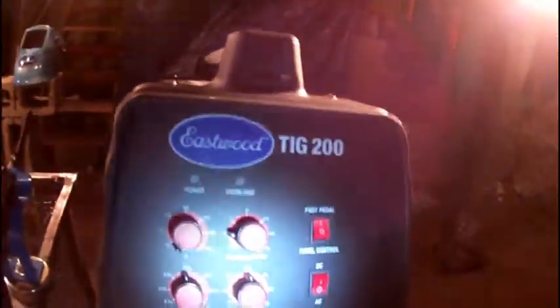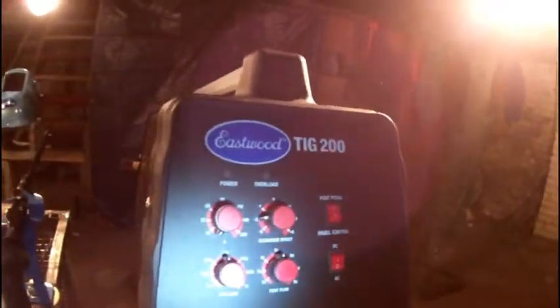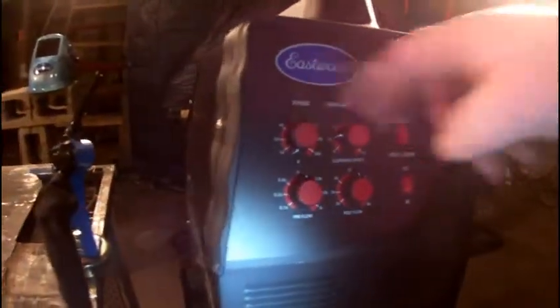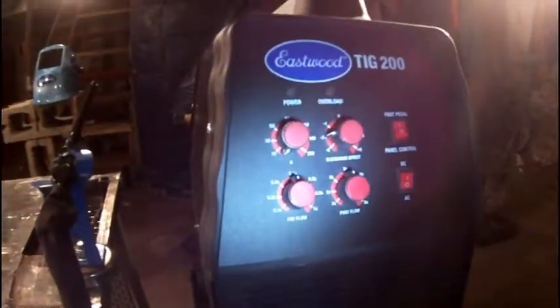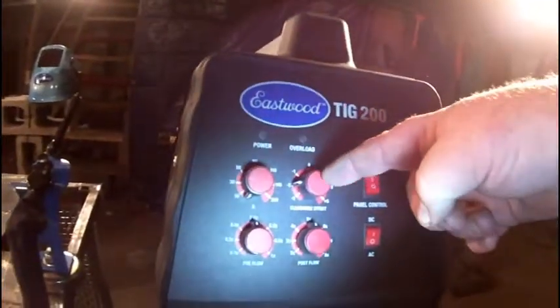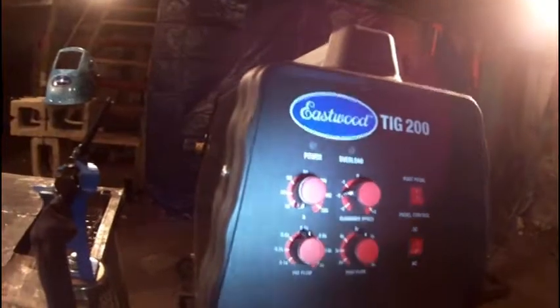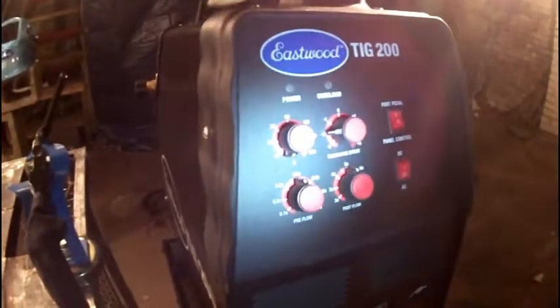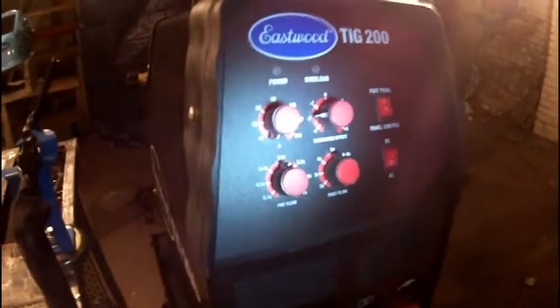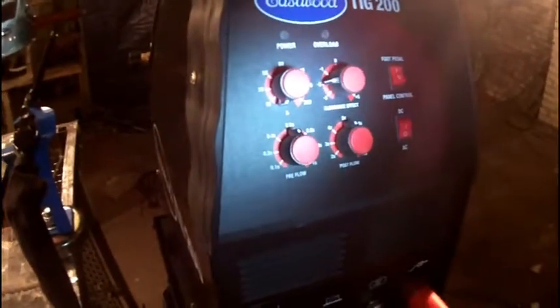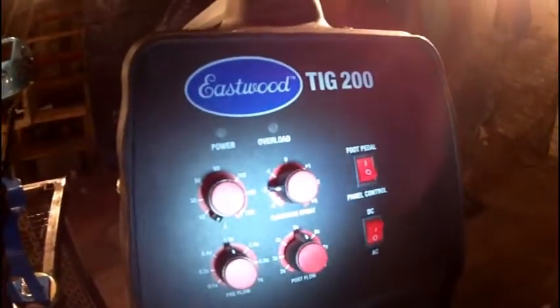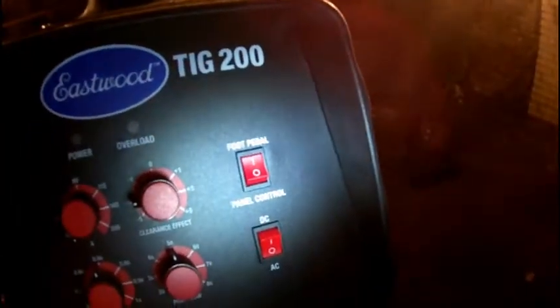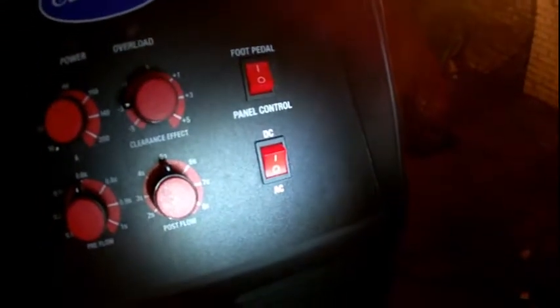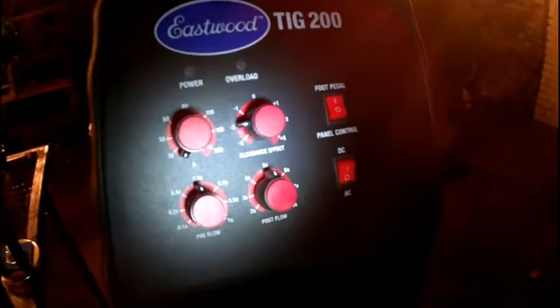So if we come around to the front of our machine here, you can see the controls, and all we have to do is set them up for aluminum. Here's our amp control. Since I'm going to be using the foot pedal, we're not going to worry about it. Next we have the clearance effect, which is already set to -3. Pre-flow, I have it set to 0.6 seconds, just a little over half a second from the time you press the pedal to the time the arc starts, and a 5-second post-flow. Amp control set for the foot pedal, and the machine set for AC. So that's it for machine settings.